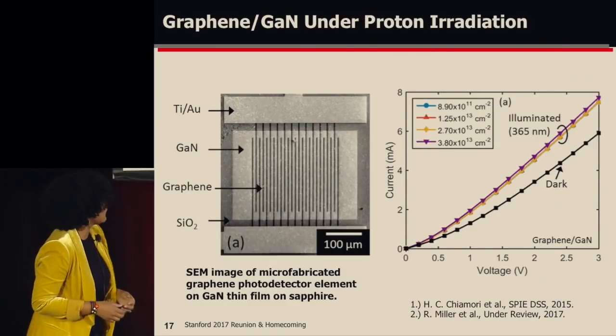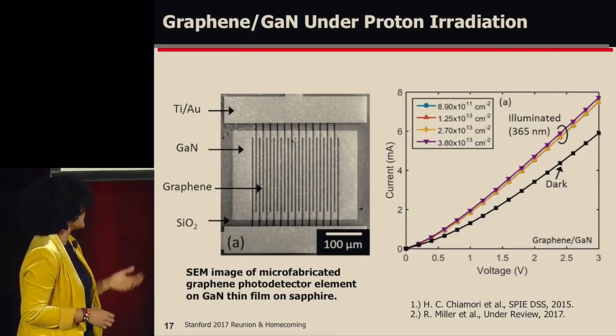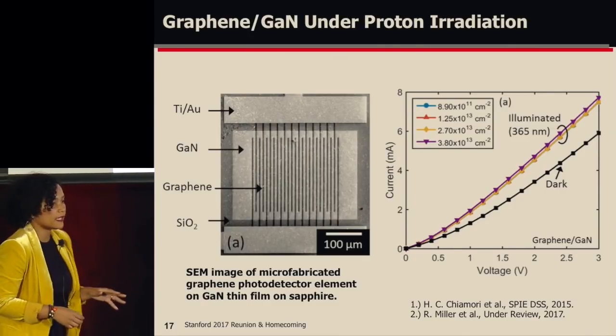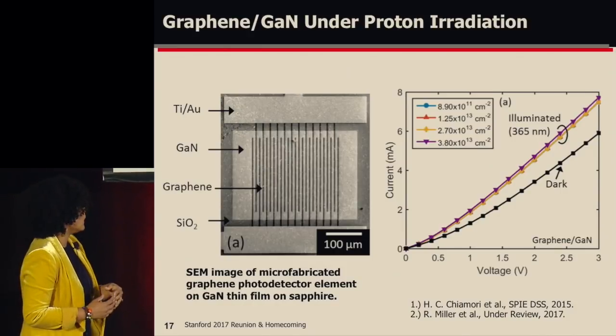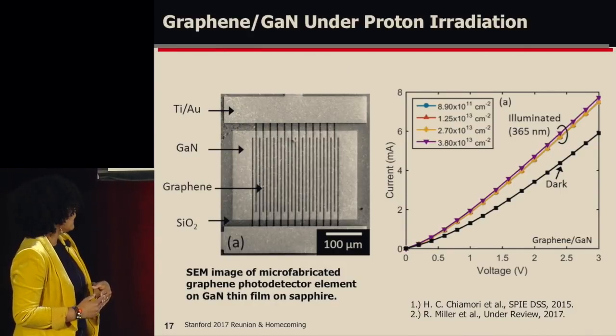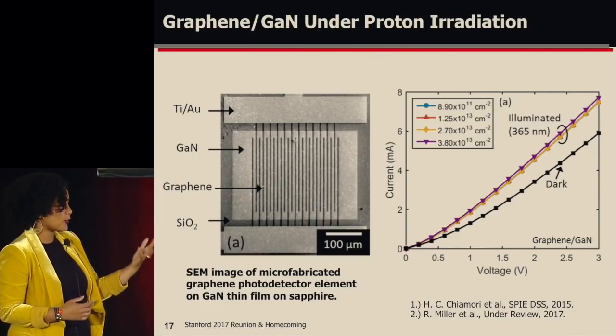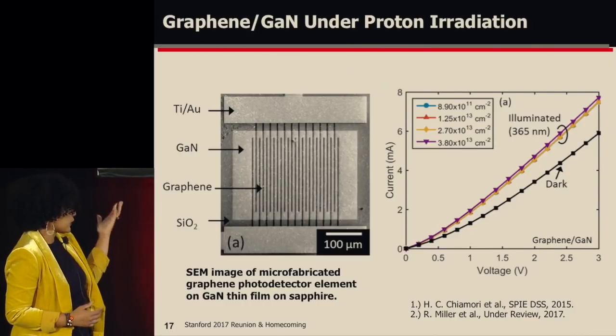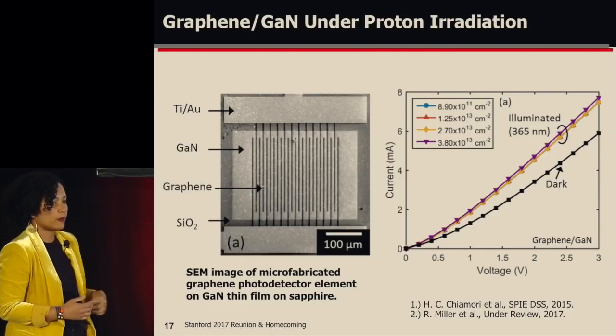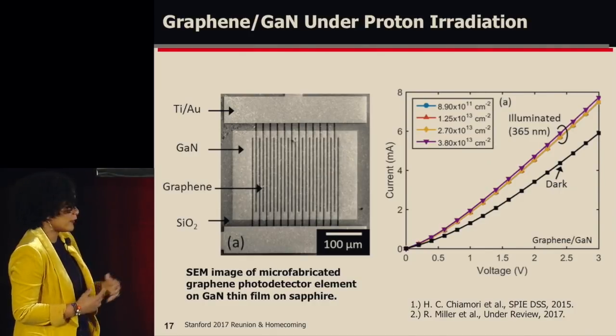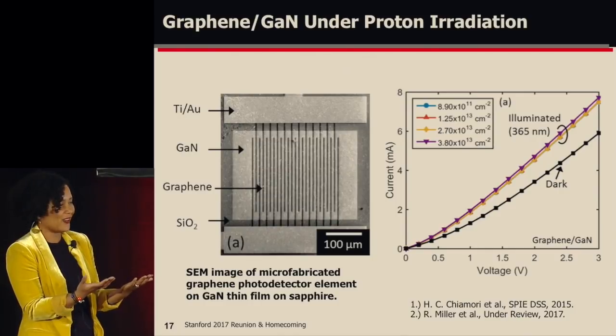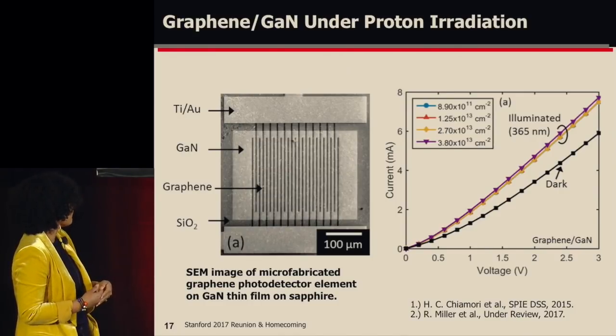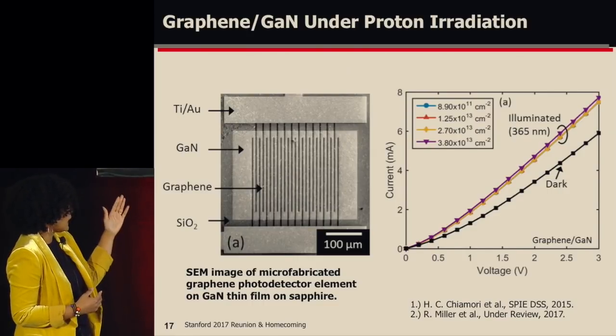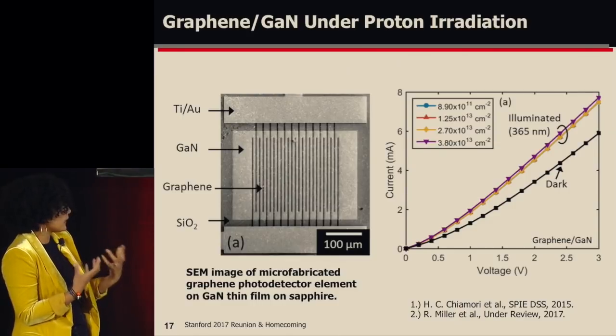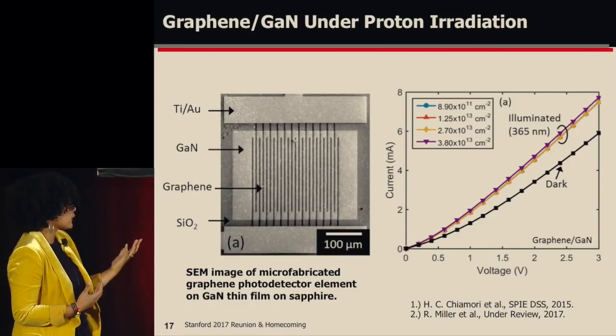This is an image of our graphene on gallium nitride device. So the black fingers there are around 10 microns in width. You wouldn't be able to see this graphene with your own eye. We actually have to use a scanning electron microscope in order to resolve the graphene and actually know that it was printed there on the substrate. So we have tested this device under ultraviolet conditions, and also we've irradiated it with protons at various fluences.